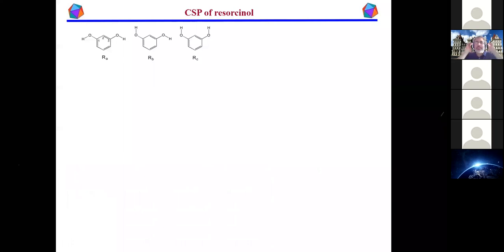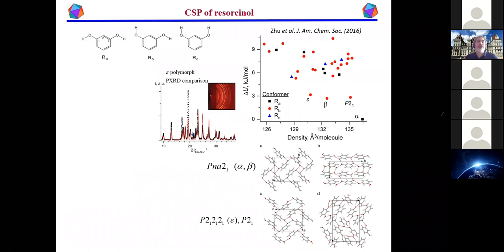Here's another example showing that you can actually predict or explore the free energy landscape and get a set of relevant polymorphs. Now, this is resorcinol. And this is an interesting case because you have a conformational dependence on the polymorphs that you get. Resorcinol is a benzene derivative. It's actually a pharmaceutical that's used in the treatment of certain skin diseases. And it has these OH groups that can either be in one of two trans-like or cis-like configurations. It turns out that the A and the B conformation determine a set of structures that, when you do a standard crystal structure prediction and you get your energy density diagram, really sit down here separated from this cluster up here.